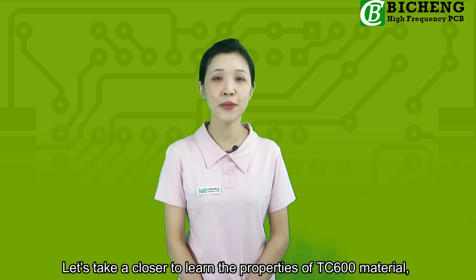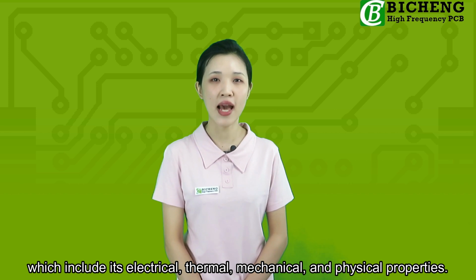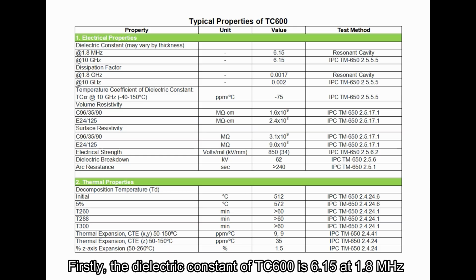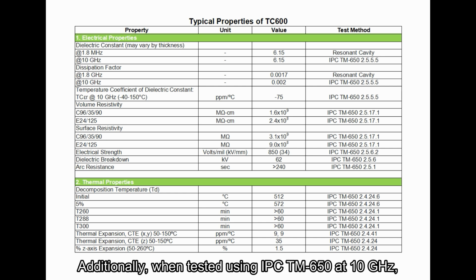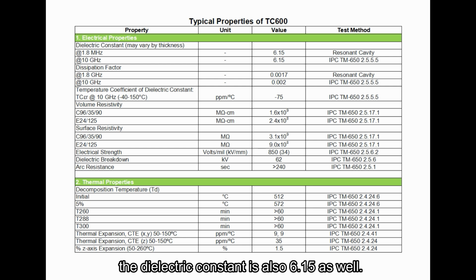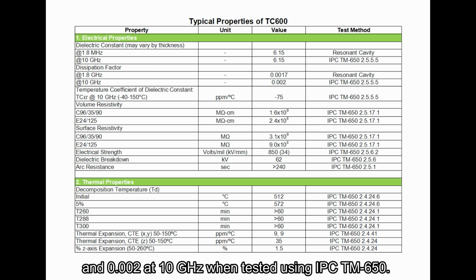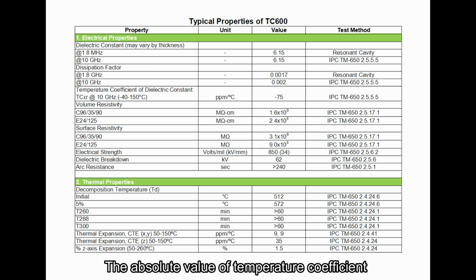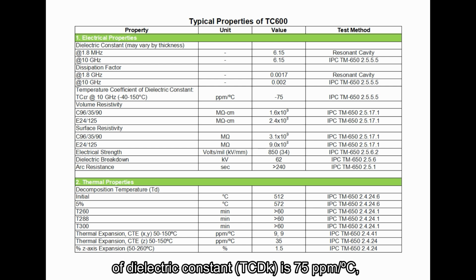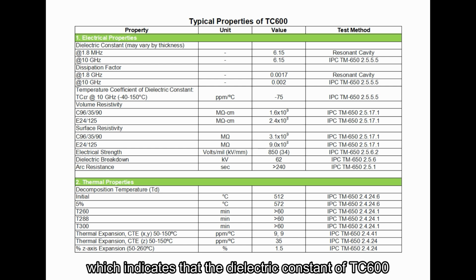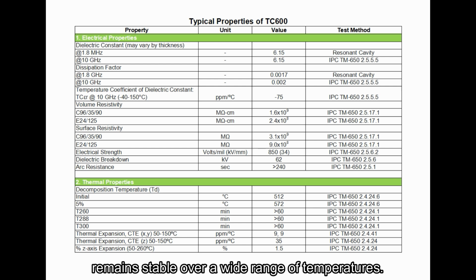Let's take a closer look to learn the properties of TC600 material, which include its electrical, thermal, mechanical, and physical properties. Firstly, the dielectric constant of TC600 is 6.15 at 1.8 MHz when testing using the resonant cavity measure. Additionally, when testing using IPC-TM-650 at 10 GHz, the dielectric constant is also 6.15. The dissipation factor is 0.0017 at 1.8 GHz and 0.002 at 10 GHz when testing using IPC-TM-650. The absolute value of temperature coefficient of dielectric constant is 75 parts per million per degree C, which indicates that the dielectric constant of TC600 remains stable over a wide range of temperatures.